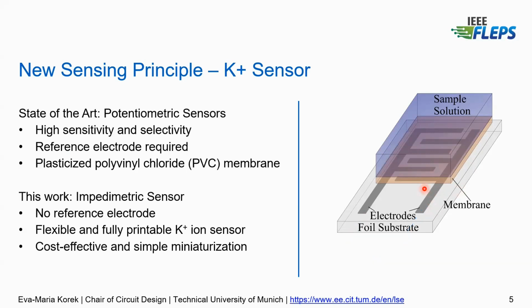So if we compare this to the state of the art, which are potentiometric sensors, the potentiometric sensors have a high sensitivity and high selectivity, but they require a reference electrode, which adds more material that is needed, and also is often prone to drift of the sensors. And they often, like all of the papers I know, use a PVC membrane, which is not printable.